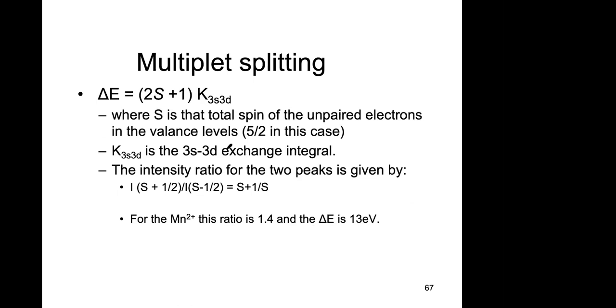And I'm not going to go over this very strongly, but you can see a difference, for example. This ratio is around, because of the spin before and after, like 1.4. You can see a change of 13 electron volts from the 3s electron.